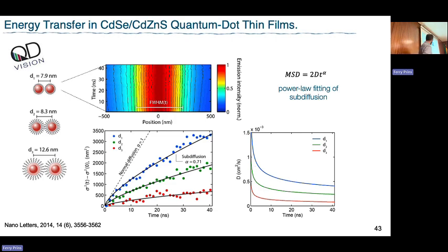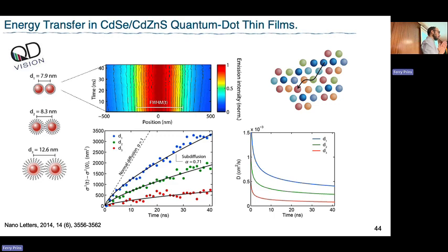This alpha parameter is 0.7—I'll get to this in a minute. The 0.7 tells you it's slowing down. Why is it slowing down? Well, these particles are actually not perfect, so there's got to be some size variation. I'm going to have some particles higher in energy, other particles lower in energy, and I excite all of them more or less with the same probability.